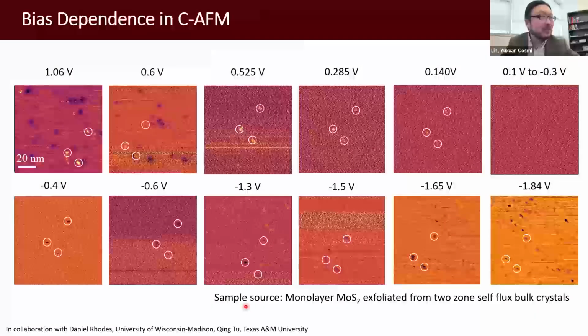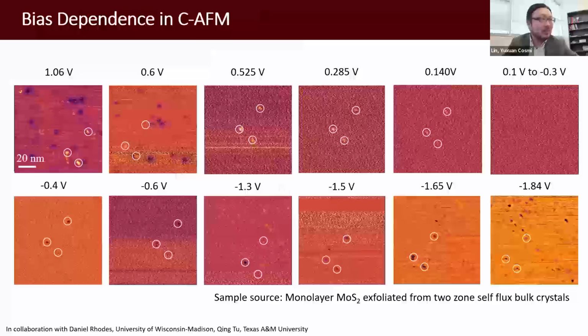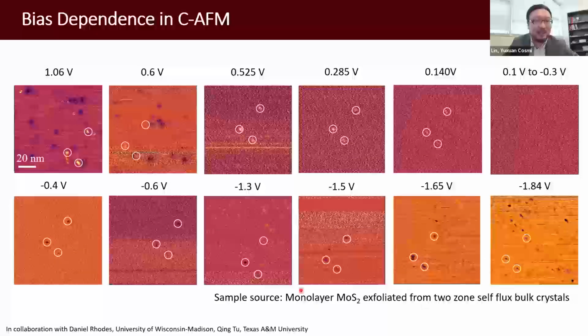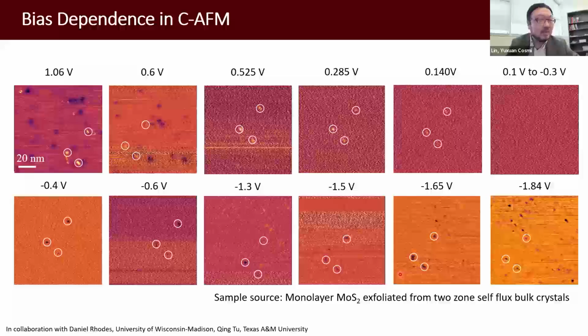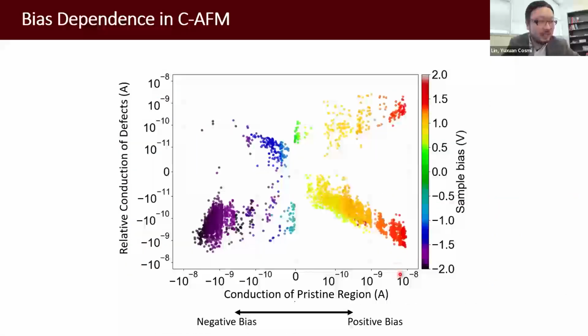There is more information. We can do bias dependence. So here are some mapping examples. We use this triangle shape as an anchor to try to align different frames. It's the same region, but with a slight drift under different bias. You can clearly see those defect features emerge, and they behave differently at different biases. We did some careful analysis.